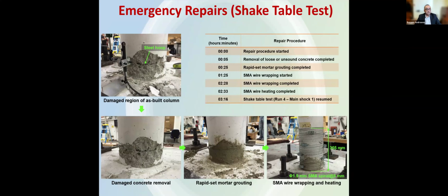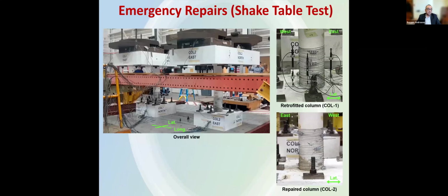So we took one of the columns that were damaged, and again, the damage here is in the form of cover spalling, exposure of the internal steel hoops. And we performed that repair process, and it took about 2.5 hours to complete that. And then the column was ready for testing. So we conducted tests on two columns at the same time. The top one actually was not damaged. That was retrofitted from the beginning. The bottom one here shown to the right is damaged and then repaired and then tested.